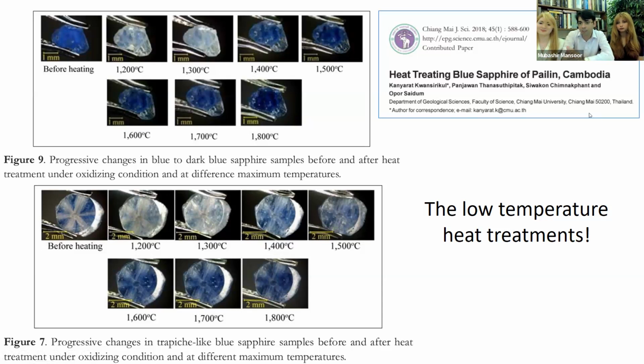What happens is, now, since these treatments occur at very low temperatures, about 1200 Celsius or so, and the geological conditions under which these sapphires' genesis occurs are also at a very low temperature, it becomes very difficult to identify these sapphires as well. And therefore, there is a lot of research going on on how to identify low temperature heat treatments. People are focusing a lot on zircon inclusions, which is very good news. Doing Raman spectroscopy on zircon inclusions in these sapphires could be a very good way of doing it. Professor Fritsch had published an article that actually showed this is a possibility. It was published quite recently.